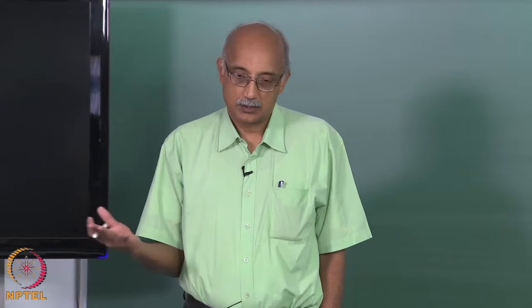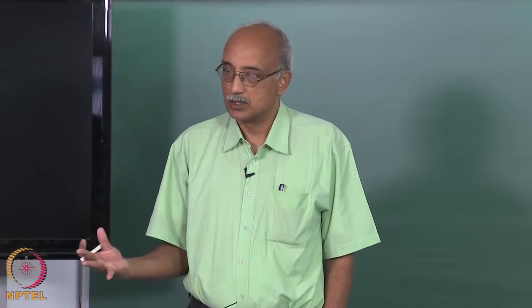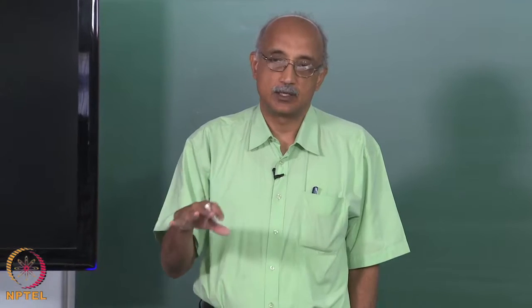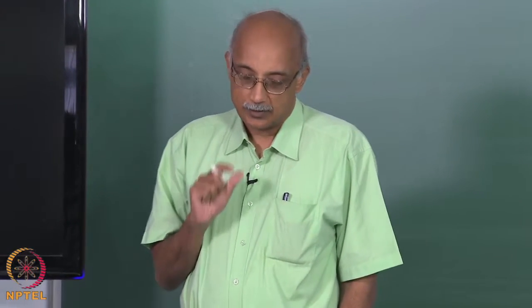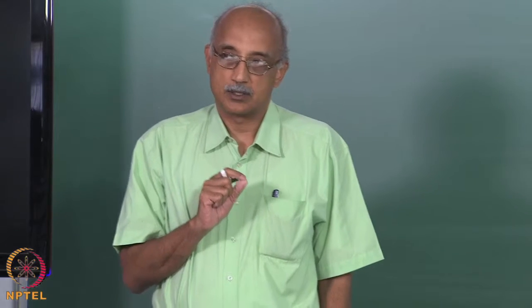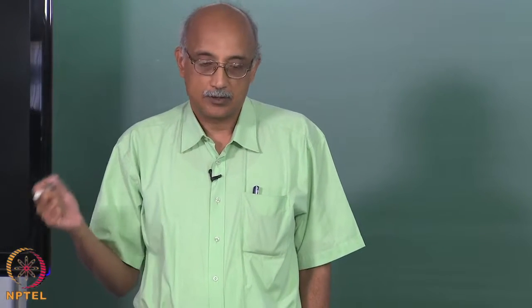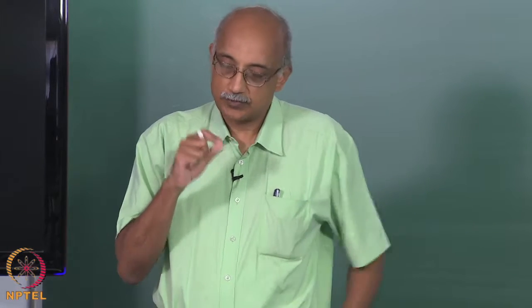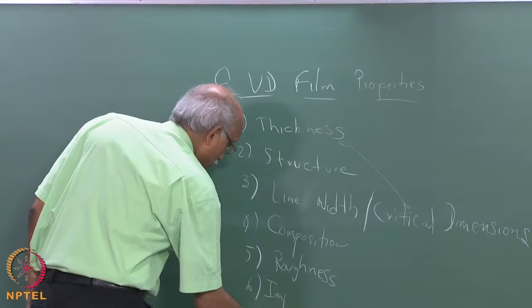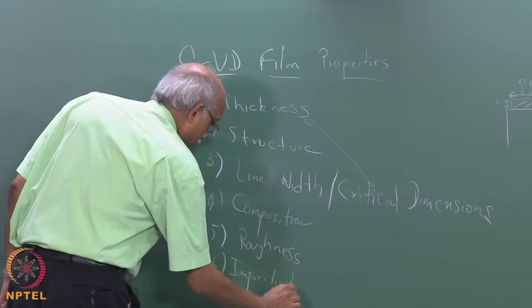When you have a substrate, it has a certain predefined roughness, but when you deposit a CVD film on it, the roughness is going to change. That can be a very important parameter in many applications, particularly when the film is trying to provide certain protection, because a rough surface, for example, will erode very differently from a smooth surface. So, the surface roughness becomes a very important parameter, and impurity levels are also important to measure.